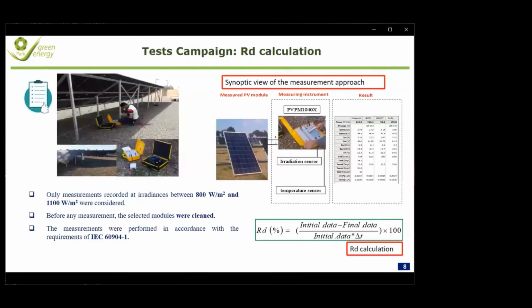In parallel, the electrical parameters were measured and compared with the ones provided by the manufacturers, and in this study, the measurement of individual modules was performed in real condition with the I-V tracer. For high accuracy of the I-V curve measurement, the measurements were taken around noon and at clear sky condition, with irradiance intensity between 800 and 1100 watts per square meter. Also, before any measurement, the selected PV modules were cleaned to eliminate the effect of soiling.